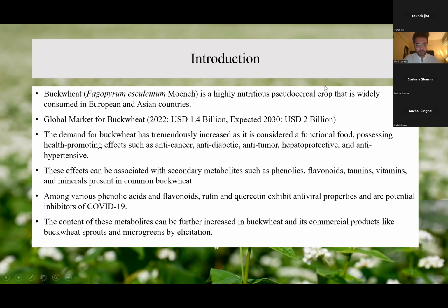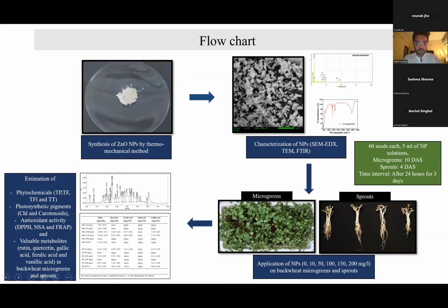And there are various products of buckwheat, such as buckwheat microgreens and sprouts, that are gaining tremendous attention. So by the process of elicitation, the content of these secondary metabolites can be further increased. So in this work, we have used zinc oxide nanoparticles for the process of elicitation. In the first step, the zinc oxide nanoparticles were prepared by thermomechanical method. Then the characterization of the nanoparticles was done using SEM, EDX, TEM, and FTIR.